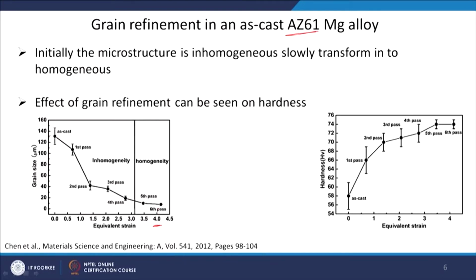So, in the as-cast material, initially they observed inhomogeneity in the microstructure. By the third pass or fourth pass, the inhomogeneity is decreasing, and by the fifth and sixth pass the microstructure is homogeneous. Obviously, considering the passes will be the amount of deformation and also the change in the direction of the deformation. So, as you are going to longer cycles or multiple deformation directions, initially it will be inhomogeneous for first and second pass.